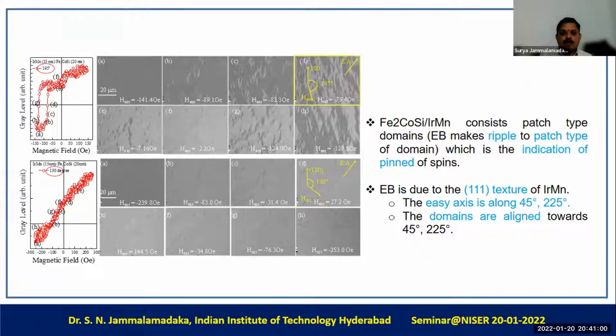We also tried to get the MOKE images at different angles, and we do see a clear shift of the magnetization loop along the magnetic field axis, even from MOKE as well. So from this, we confirm that indeed there exists an exchange bias in our film without even field cooling, which could be due to the 111 texture of the iridium manganese thin film.